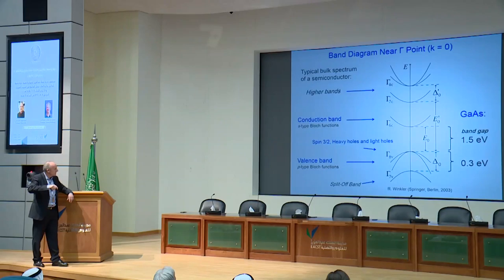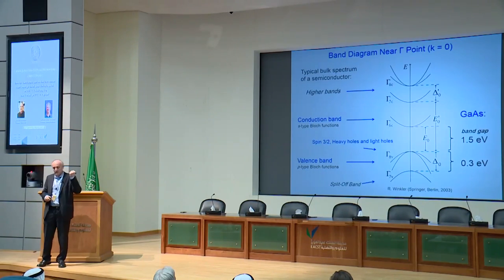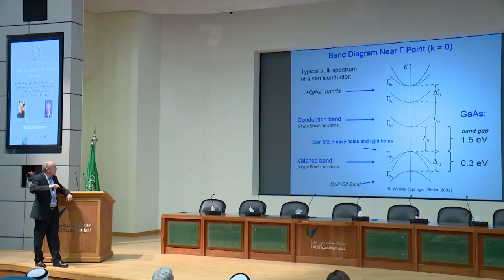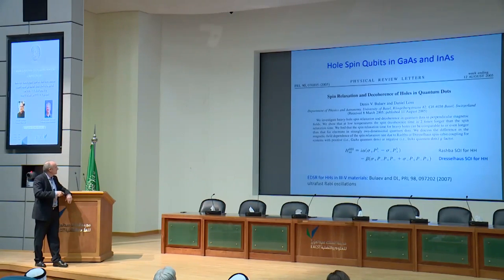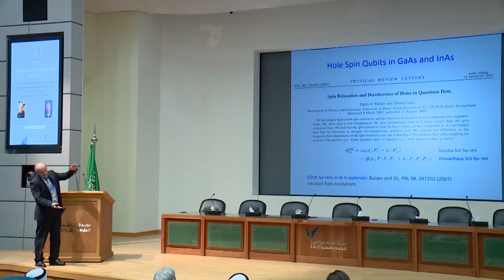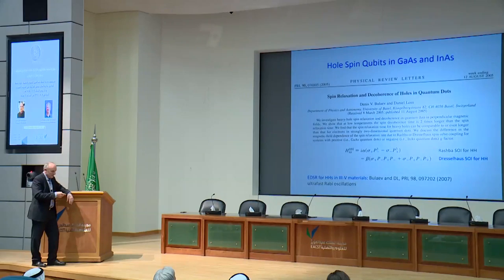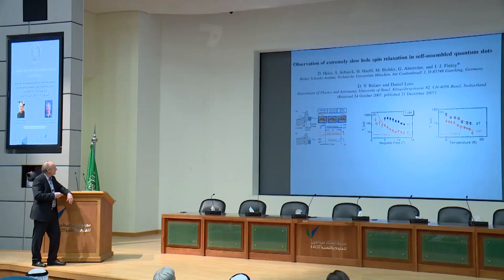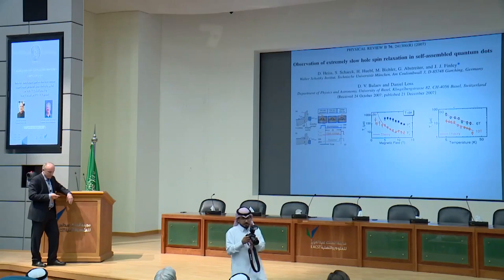And that makes a huge difference because a P-wave is a wave function which has no overlap at the center of the atom, whereas an S-wave has. And that means the hyperfine interaction is much stronger in this case than in that one. So holes, from this point of view, could be promising. And indeed, we looked into this many years ago and proposed a new scheme, basically also by compressing your system and lifting this degeneracy, very similar to what Lawrence was also showing you, and showed then that indeed you get very, very long T1 and T2 times of hole spin qubits.